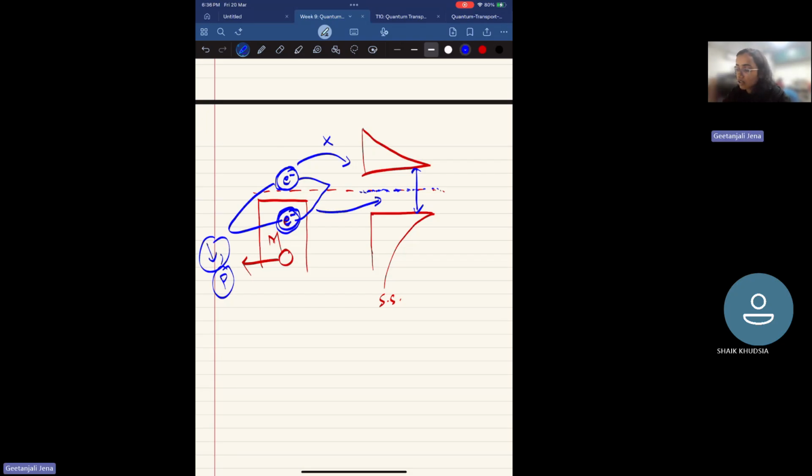So this is what we call the Andreev reflection: even under the low bias condition, we see a conductance because of this combining of electrons of opposite spin at the Fermi surface, and to equate the charge, one hole will be reflected back into the metal.